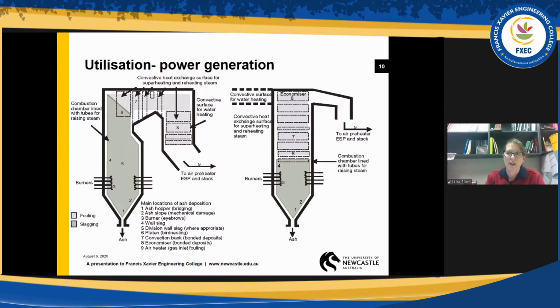So if they are allowed to sit on the tubes for too long, they will actually sinter, possibly melt, form strength and be impossible to remove. And having an extra layer on your tubes affects your heat transfer. So you won't be able to get the heat transfer you're expecting if you keep building up a layer on those tubes. So they're the big issues.